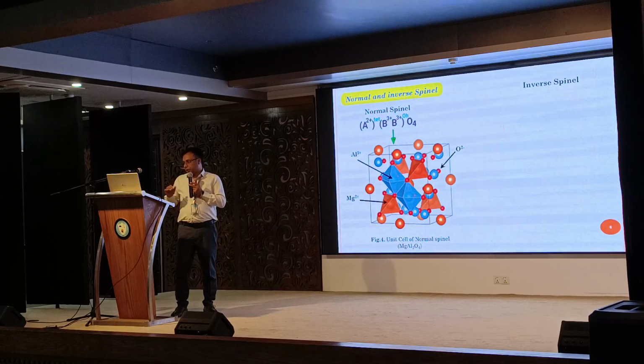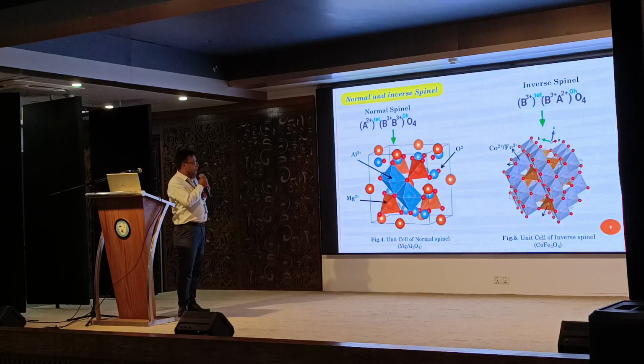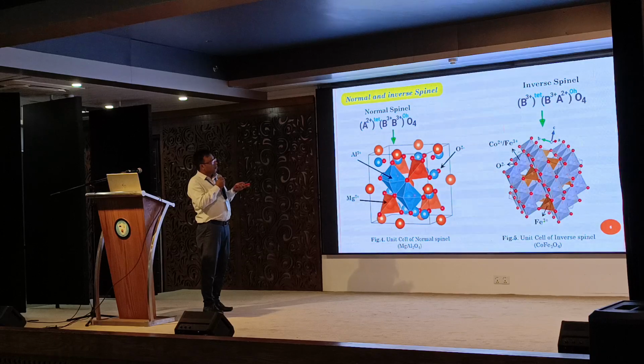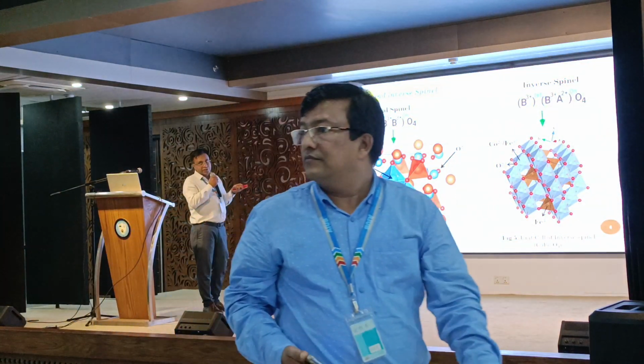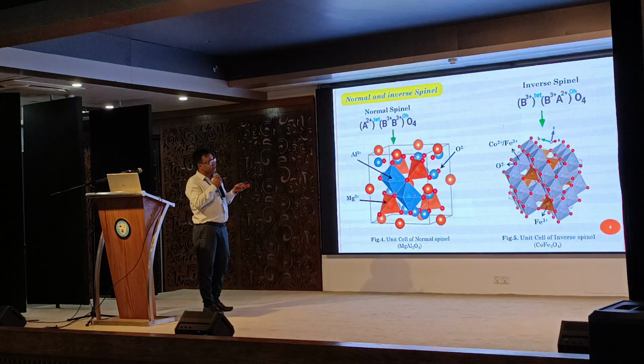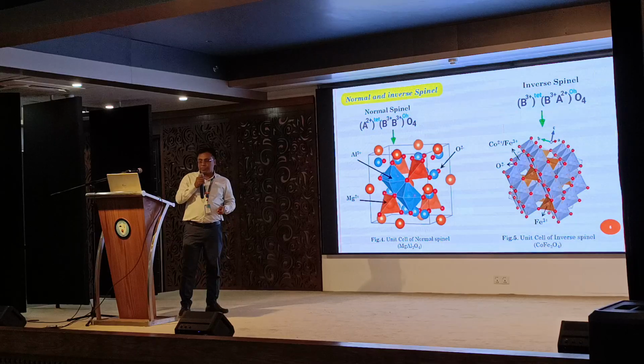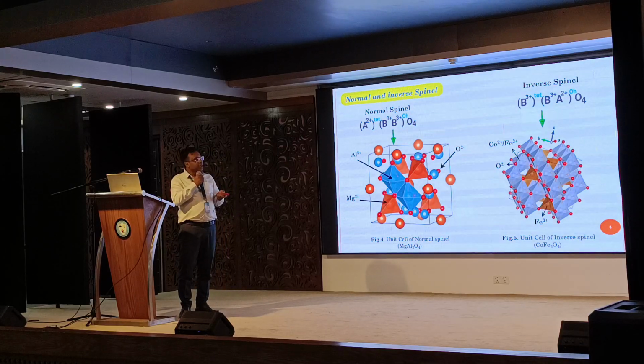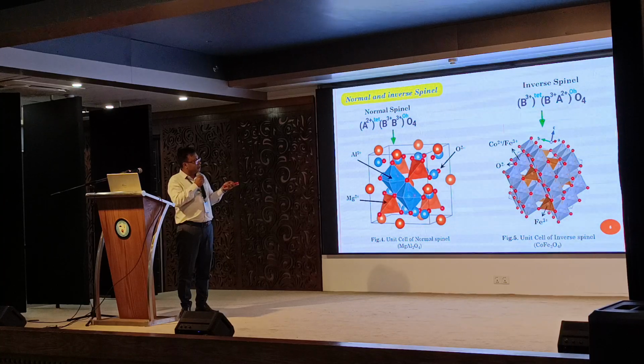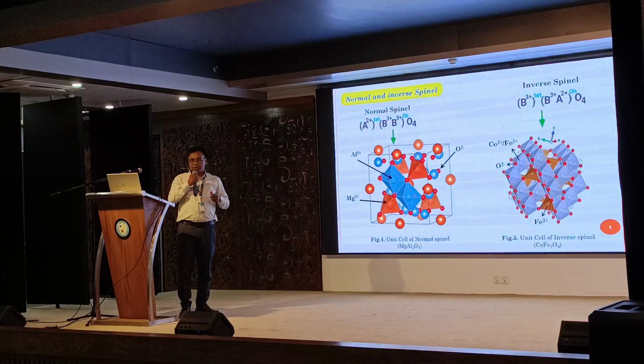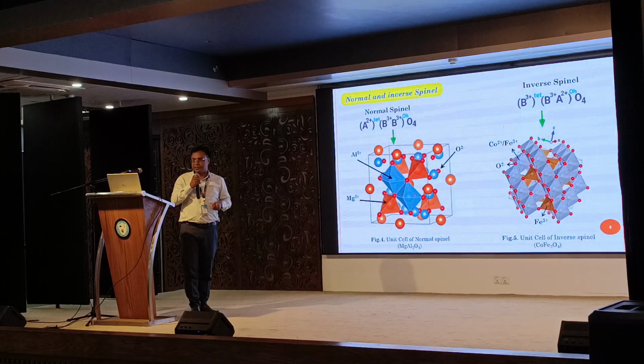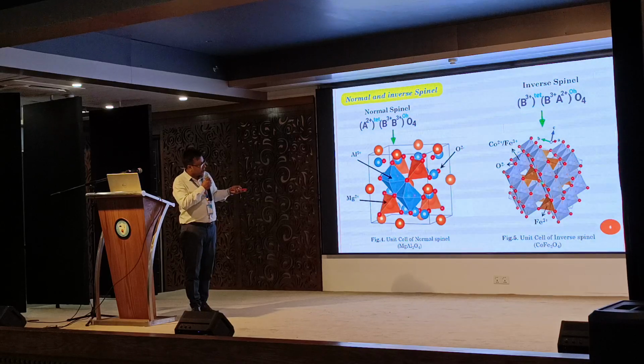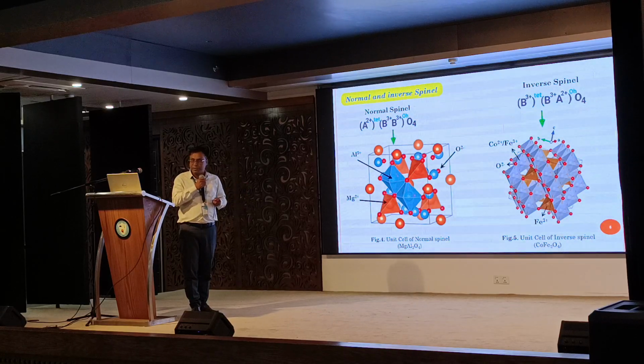So I would like to explain the inverse spinel, where one element from the octahedral site is replaced to the tetrahedral site, that is B3 plus, and for spinel nanoferrite it is Fe3 plus iron. From the octahedral site, one iron is shifted to the tetrahedral site, and from the tetrahedral site the divalent atom is shifted to the octahedral site, then we call it inverse spinel. It also depends on the chemical stability whenever we are making the samples, so we have to note that. This sample we made, and we found it is inverse spinel.